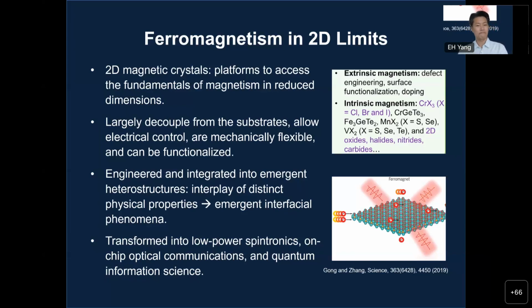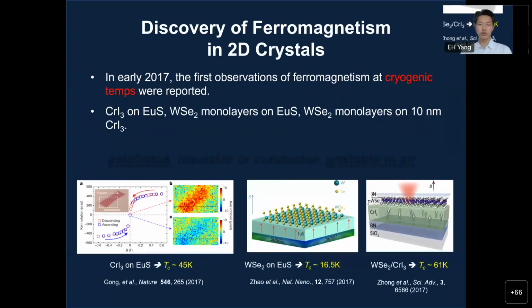All right. So the first discovery of these 2D magnets was in 2017. Those three materials, I believe, are chromium triiodide on ferromagnetic sulfide, tungsten diselenide monolayers on the same sulfide, and tungsten diselenide monolayers on 10 nanometer chromium triiodide. So basically, this sulfide is a magnetic material, and this tungsten diselenide is a non-magnetic material. What happens is tungsten diselenide becomes a ferromagnet through magnetic proximity coupling.